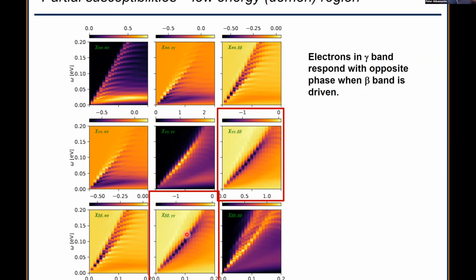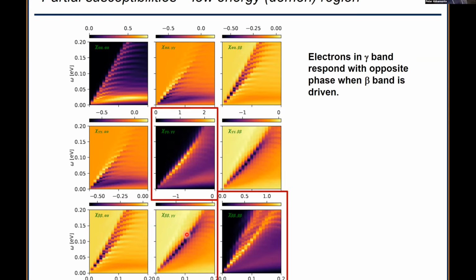So as you can see, if I drive the gamma band, then the gamma band responds in the normal way because that's the one I'm driving. But if I drive the beta band and look at how the gamma band responds, it has the opposite sign, which means this mode in RPA is a demon mode. Doesn't necessarily mean the experiment is a demon, but the mode in the RPA is clearly an out of phase mode between the gamma and beta electrons. The alpha band seems to be a spectator that isn't really participating for some reason. But yeah.